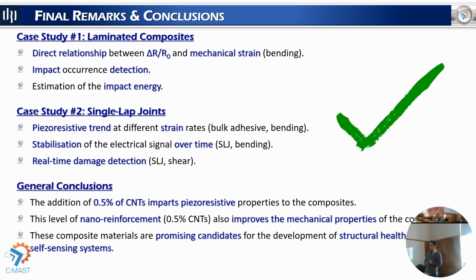In the second case study of the single lap joints, we also observe a good piezoresistive trend that varies according to the different strain rates that were applied in the bulk adhesive in bending mode. We also see a stabilization of the signal over time for the single lap joint, and in the real-time damage monitoring, we can detect the different moments and the different cracks that happen in the joint during the shear strain tests. So, general conclusions about the work and the project.